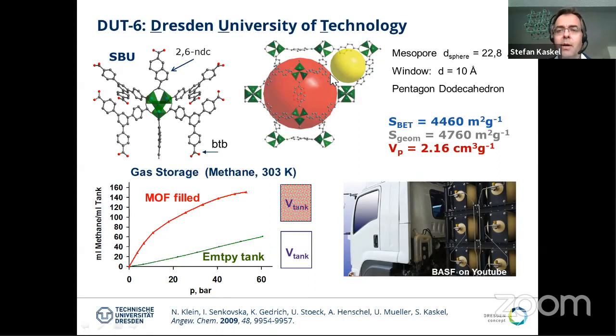And for us, it was quite a milestone because for the first time we achieved more than 4,000 square meters per gram surface area in this kind of hierarchical material, where basically the zinc 4O cluster is the building block, and then a trifunctional linker is used to connect these zinc 4O clusters, and a bifunctional linker is used as a cross linker. So you can also regard this as a crystalline copolymer in a sense, which basically stabilizes. This is a very rigid architecture basically that allows then to sustain the stability during the adsorption.